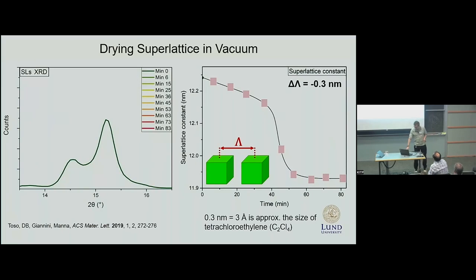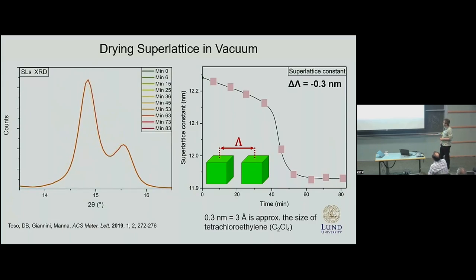So if you put it under vacuum and start collecting diffraction patterns, you see that the shape of this peak evolves over time, over about 90 minutes, an hour and a half. Here's shown a superposition of what the peak looked like before and after. By performing the fit like I showed before, we can track contraction of the superlattice over time, and the magnitude of the contraction is approximately compatible with the size of the solvent molecule tetrachloroethylene.